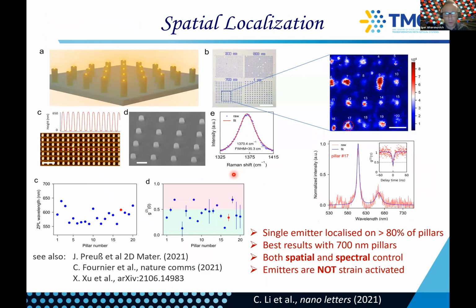So moving on, we also wanted to have some sort of XY localization. And so here we try to grow directly on pillars. And there are two motivations here. One is, of course, creating this spatial localization. And the other motivation is to try and grow on dielectric directly. And so growing on dielectric is actually quite challenging, but very important if you then want to grow, for example, on a cavity, directly on a cavity.